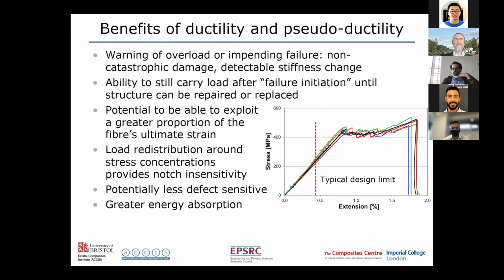So what are the benefits of this ductile or pseudo-ductile behavior? So by putting this sort of behavior into the material, we get a warning of overload or impending failure. We get non-catastrophic damage, and we also have a detectable stiffness change. This gives the ability to carry load after this so-called failure initiation point until the structure can be repaired or replaced. We can also potentially exploit a greater proportion of the fiber's ultimate strain.